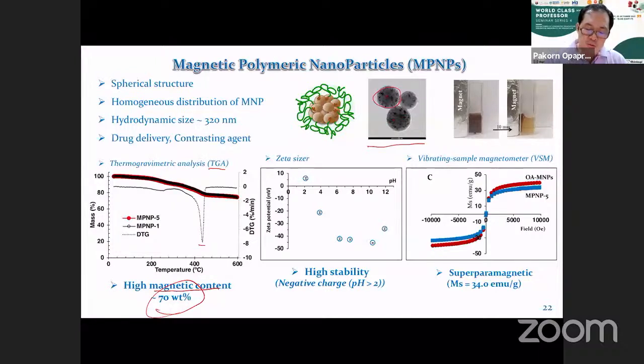This shows superparamagnetic properties. Therefore, they can be influenced by an external magnetic field. So we can disperse them in water very well, or we can collect them back using a magnetic field. In only about 5 to 10 minutes, we can collect all of these particles. They are very stable in water because they have a very high negative zeta potential, which comes from the carboxylic acid in the structure.